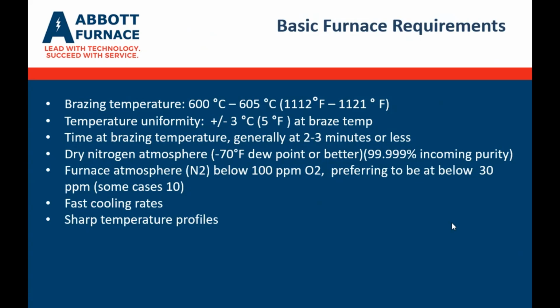And then when you're looking at fluxless brazing, for example, you're looking at very, very low oxygen levels in there, in some cases less than 10. So we are looking at a very clean, high purity atmosphere. Generally, the lower the ppm of oxygen is, the better cosmetic or shinier appearance your heat exchanger post braze can have. Obviously, we've talked about before the fast cooling rates and sharp temperature profiles are advantages for good quality parts as well as lowering utilities.